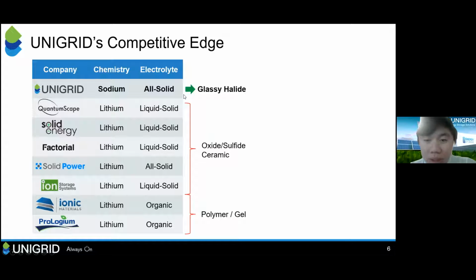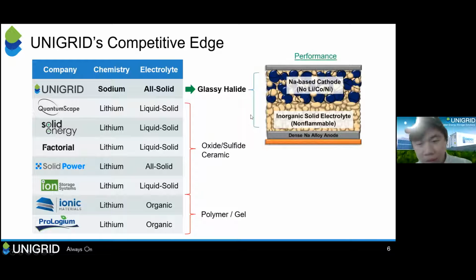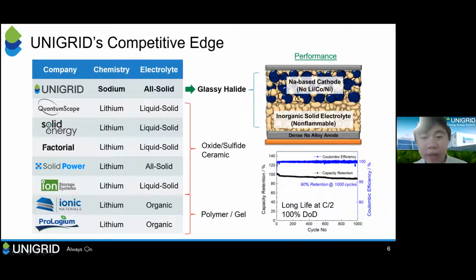Secondly, we also adopt all solid systems with absolutely no liquid in them. Most companies still use some kind of organic hybrid. And we can achieve this because we adopt a quite novel halide-based solid electrolyte, which no other company has used before. This unique solid electrolyte combines the stability of conventional ceramics and the processability of glasses to improve the performance and also demonstrate very impressive behavior. So to date we have gotten about 1,000 cycles with 100% depth of discharge and a 90% retention, in a laboratory-scale cell. It's quite small right now, but still exciting to work on, and we're looking to scale that.